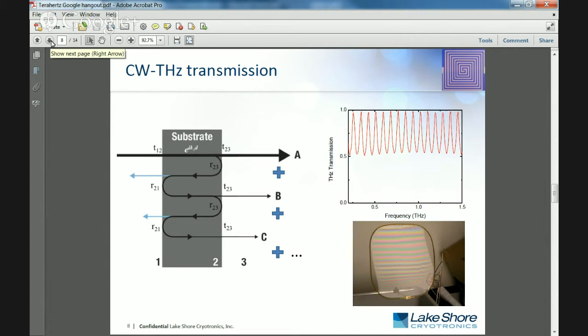But with continuous wave terahertz spectroscopy, our approach to how we do our signal analysis has to be a little bit different. Because we're using a continuous wave source, there are multiple reflections of the terahertz that happen inside of the substrate. And when we look at that terahertz light with the detector, what we see is really an interference of these multiple passes through the substrate.